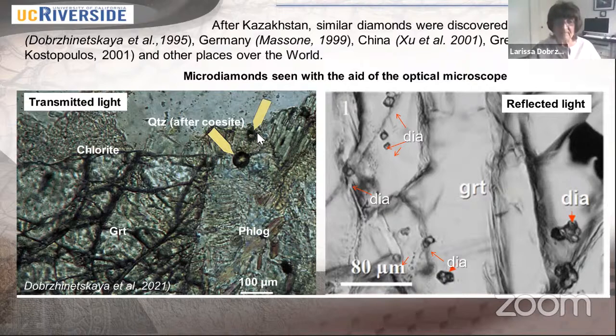It's not very well seen. However, when I show these samples to students, I usually tell them, when you look at it in the microscope, you see a mountain. Diamonds usually, because they have a very high refractive index, look like a mountain. And here I show you a similar sample in reflected light, the polished surface of the thin section. You see here diamond, diamond, diamond, a lot of diamonds. There are 1, 2, 3, 4 crystals of diamond, all of them sitting inside of garnet.